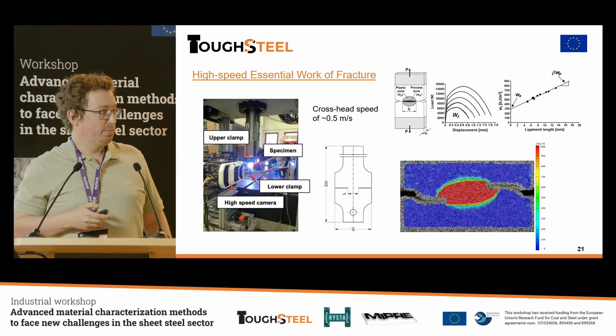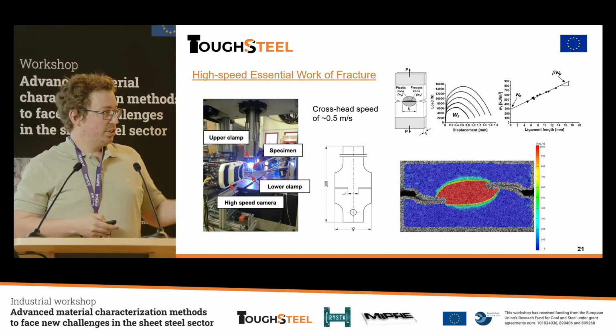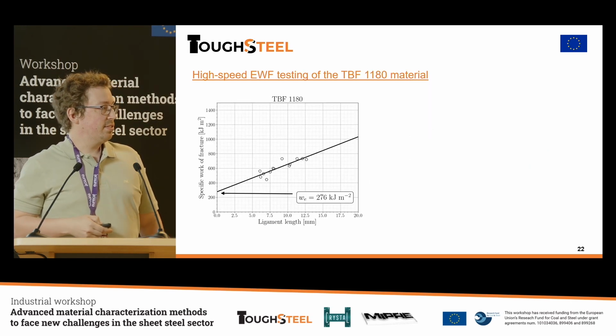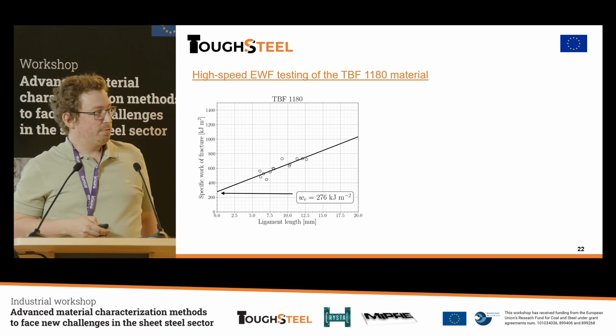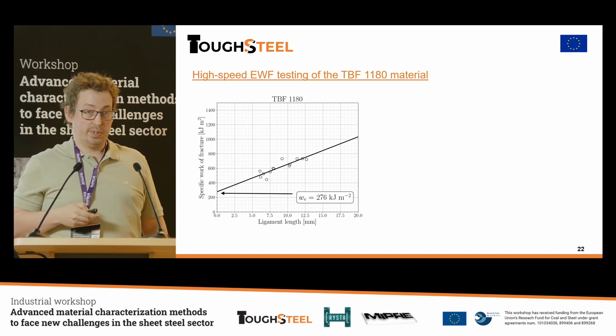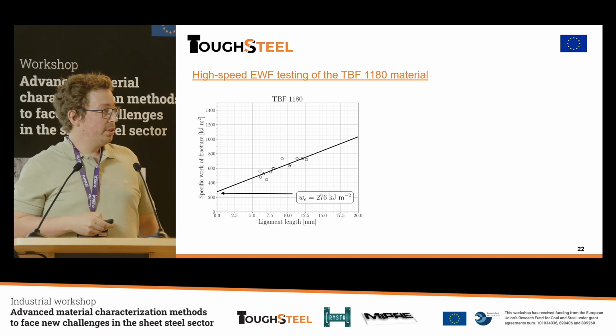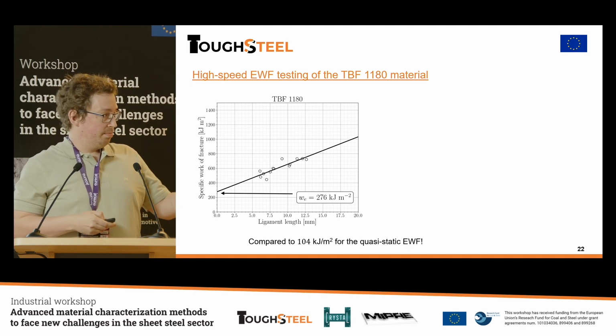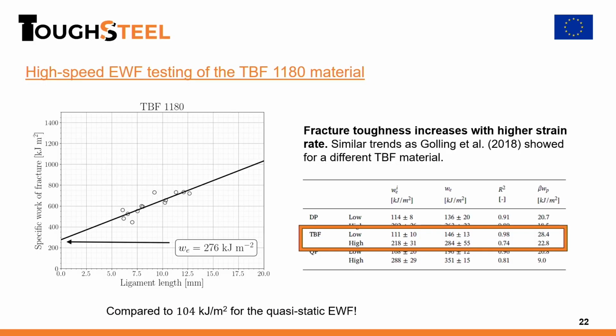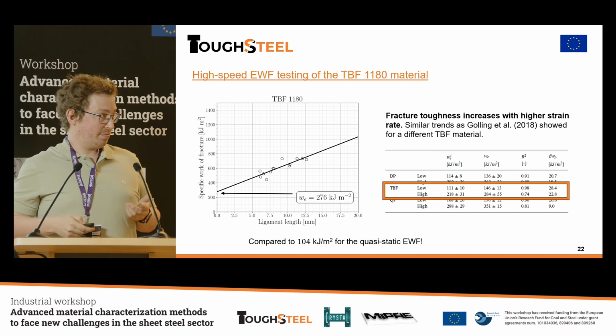It's been described by Laura before, so I won't go into detail. But you do the same methodology, and you receive this. And you can see that the essential work of fracture value there is significantly higher than 104 that we got from the published paper. Yeah, as you can see there. And it's something we can see from the published results for another TBF grade as well. It's not the same steel, but you can see that the essential work of fracture is significantly higher with the increased strain rate. So this, of course, makes it very important to take into account, for example, if you want to use it in modeling, in crash, that we need to take the strain rate into account.